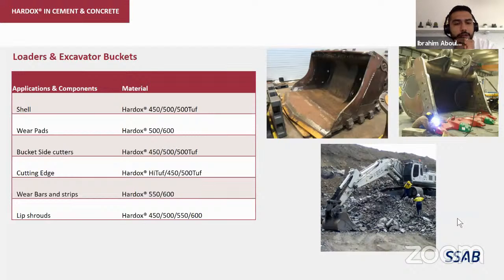Then we have the wear bars and the strips, which are also 550 or 600. The reason, again, is that it's mainly straight sliding wear. There is not a lot of impact, and that gives an advantage for the Hardox 600, as there is no impact at all. Then we have the lip shrouds on the front, which can be produced in different shapes and in different ways from Hardox 450, 500, 550, and 600. Since there is also not a lot of impact, they are more or less protected by the teeth. Next slide.